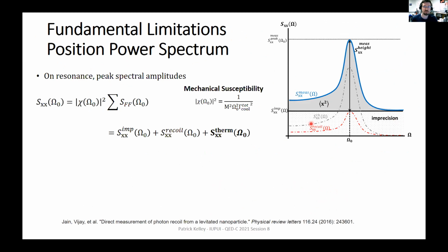So I'm on resonance, so at the peak of our spectral amplitudes, what we're looking at is the contributions that would contribute to this spectral profile. And we have imprecision, recoil, and thermodynamics. So I'll cover imprecision and the recoil in a later slide. But the leading term, the largest contribution, would probably stem from this thermal part here. So this would be basically our upper limiting contribution. And so this is going to dominate our spectral signature here.